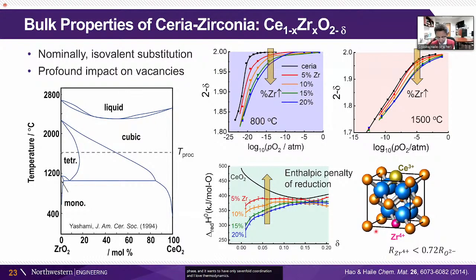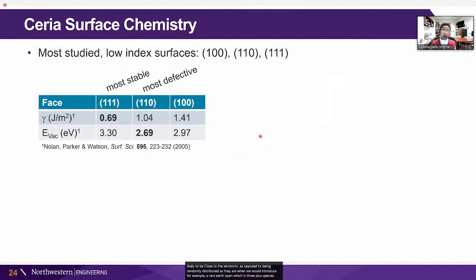And I love thermodynamics because it allows us to give anthropomorphic qualities to inanimate objects. So zirconium wants to only have 7-fold coordination. It can kick out an oxygen ion as long as the cerium agrees to adopt the 3+ oxidation state. And so there's a synergistic effect between the two, which allows the material to be more reduced when we introduce zirconium, despite the fact that the zirconium remains in the 4+ oxidation state. Okay. All right, great. That would tell us that oxygen vacancies are likely to be close to the zirconium as opposed to being randomly distributed as they are when we would introduce, for example, a rare earth dopant, which is a 3+ species.